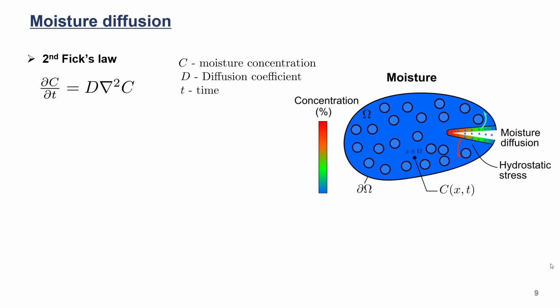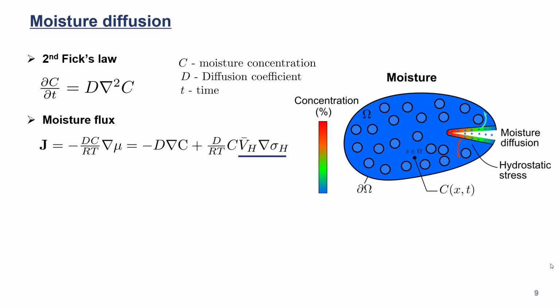For the moisture diffusion, it follows Fick's second law. Basically, it describes that the rate of change of the concentration is proportional to the diffusion coefficient and the gradient of concentration. Then we can write the moisture flux. It describes a certain amount of moisture across the unit surface area. Here, the new element we introduced is considering the hydrostatic stress, because this stress inside the materials can influence the diffusion process. The higher the hydrostatic stress, the lower the amount of diffusion can occur.